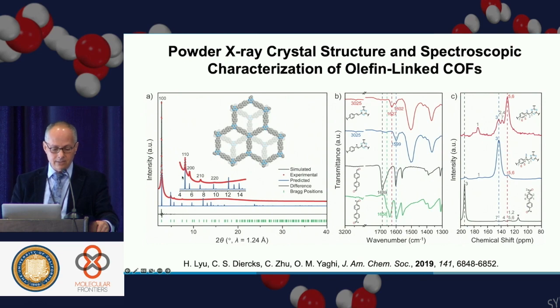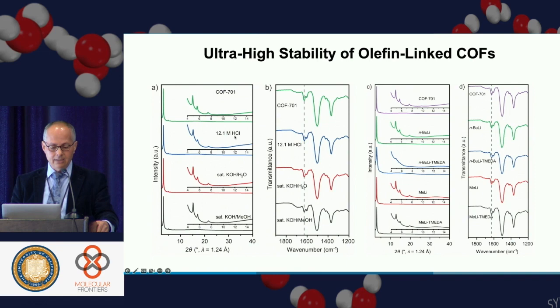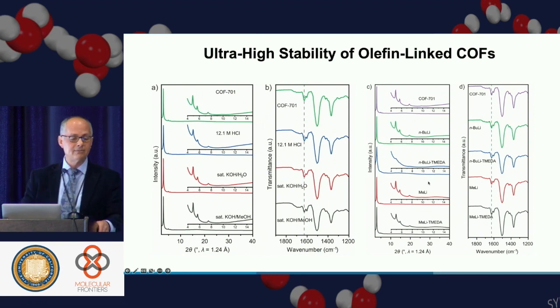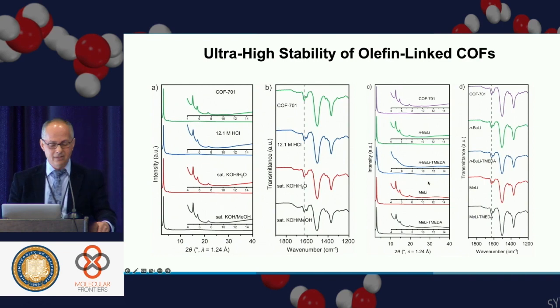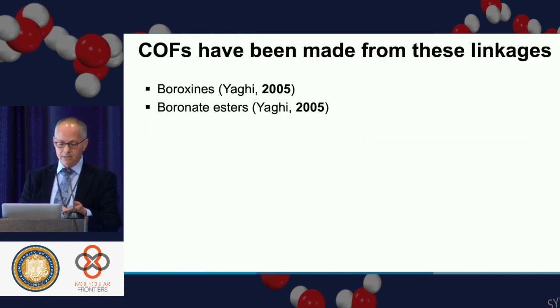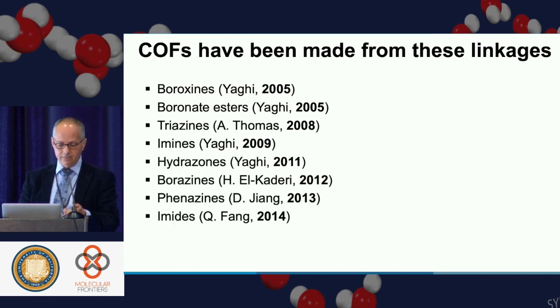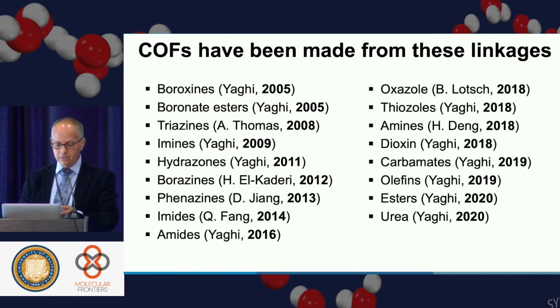This is how crystalline the material is, and it's extremely stable in 12 molar HCl, saturated KOH, even corrosive environments like N-butyllithium. Why? Because it's made from carbon-carbon bonds, very, very stable bonds. So, COFs based on these linkages have been made by our group and others. You can see here many, many linkages that organic chemists thought are irreversible. Now we can make them reversible and crystallize them.